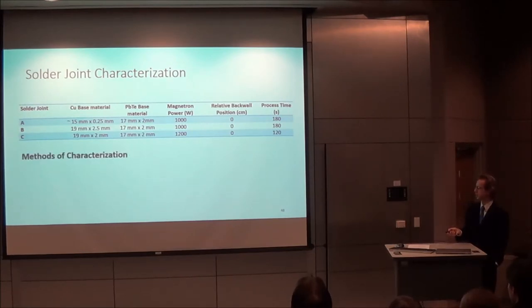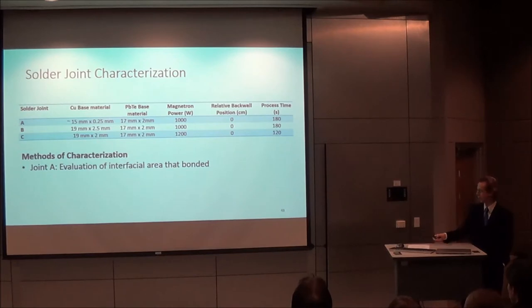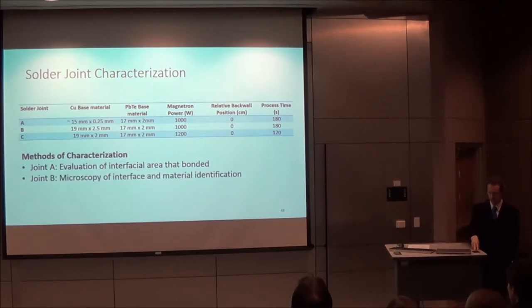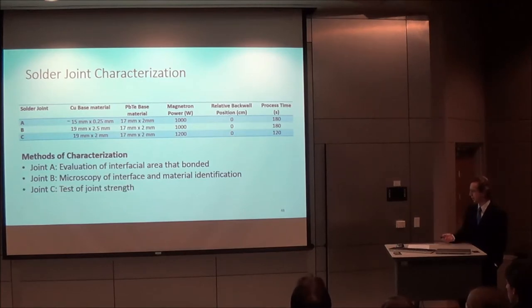And so these joints were characterized in three different ways. Joint A was evaluated to compare the interfacial area that was bonded as compared to a previous joint made without pressure. Joint B was evaluated using a scanning electron microscope to look at the interface and check for diffusion across the interlayer, cracking of the ceramic, this bonding of the ceramic with the solder, and to identify the different materials. And then joint C was tested for shear strength.